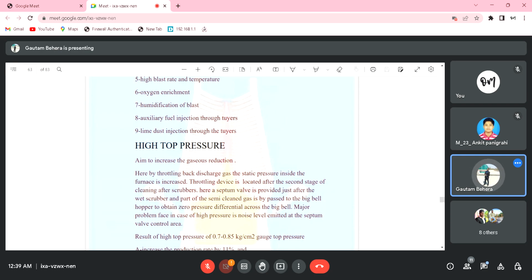And another point you have to remember is the hearth temperature. Nowadays they are maintaining a very high hearth temperature, like 1400 degrees centigrade, 1450 degrees centigrade. In Japan, this is the practice they are following. But in India, I'm not sure about that. In earlier days, they used to maintain a maximum hearth temperature of only 1250 to 1300. But in Japan and some other countries, they are maintaining a very high hearth temperature.